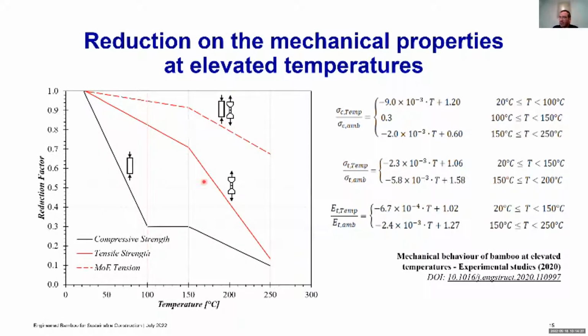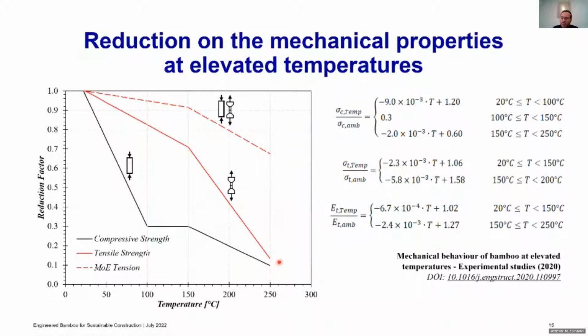And then after 250, we found that the material strength was practically lost. So it was hard to make tests above that temperature, because the samples were pretty much all char and really, really hard to test. So that's why we decided that after 250, we wouldn't use the material at all.